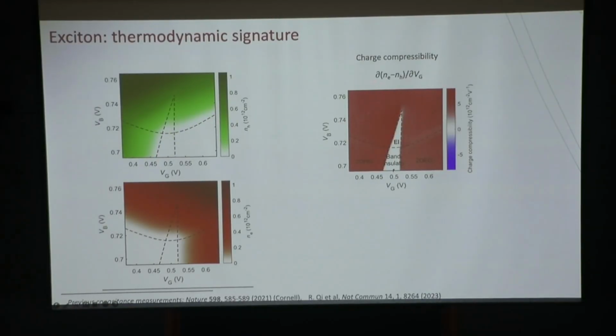So here, we are plotting the net charge, which is electron density minus hole density. If you add any net charge, this will be non-zero, and we take the derivative against the gate voltage, which allows you to change the net charge density. And it has an interesting behavior here. The red part means it's compressible. That means you can add single, individual electrons or add individual holes. And then the white regions are incompressible. That means you cannot add electrons or holes by themselves.